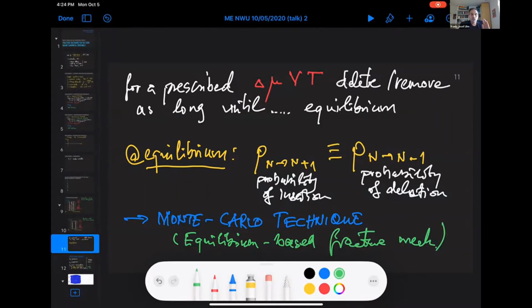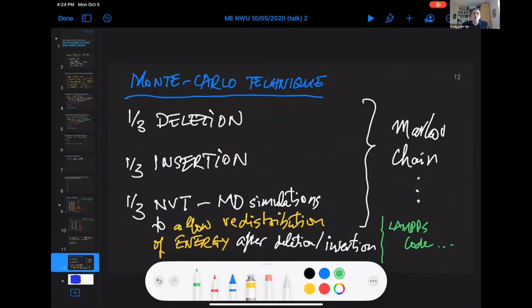Okay, so now you ask yourself, how do we actually run these simulations? You basically break down all your moves into three parts: one third deletion, one third insertion, and one third you run MD simulations to allow the redistribution of energy, because when you have a strained system and you take out a bond, the energy is redistributed. So you randomly make this move, and by doing so, you create a Markov chain, and all this is well coded in the LAMMPS code. So I leave it there. The rest is technique.